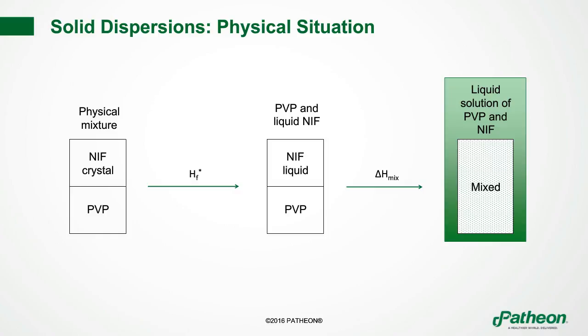Once you melt the crystal, then you've got liquid nifedipine at an elevated temperature and PVP at an elevated temperature, and that's when they begin to intimately mix. Now, when they mix, there could be heat released or there could be heat absorbed, and that's actually what we can try to measure. So if the amount of energy required to actually melt the crystal and then form an intimate solution is less than the actual heat of fusion, then there was some exothermic reaction and there was heat released upon mixing. And that's what you see here, that there could have been a negative delta H mixing, a release of heat, to give you this mixed system, which means that when nifedipine as a liquid and PVP as a powder are mixed, that's a favorable mixing that's occurring, at least enthalpically speaking.